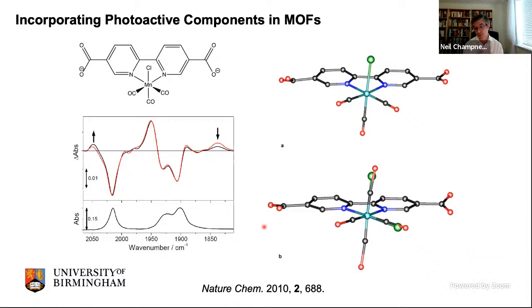We do this at the Diamond Light Source, the synchrotron, because it gives us better data. And we can isomerize from the FAC isomer to the Mer isomer. Now you can actually see that this just corresponds to this chloride moving from this axial site to this equatorial site, like so. And you can follow that and you can model the chloride in this position, and 30% of the structure has isomerized. And this was interesting back in the day because you could actually follow a simple isomerization process, photochemically induced, by single crystal X-ray diffraction using this type of approach.